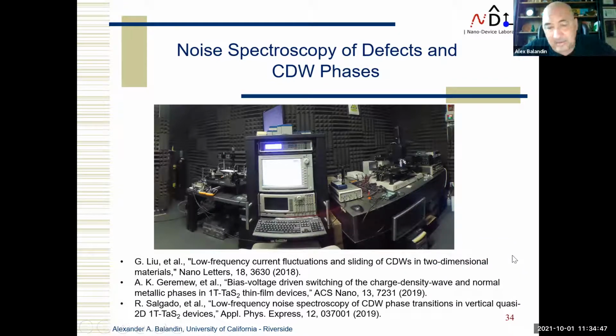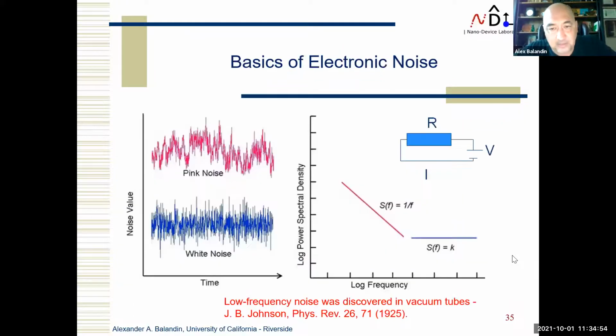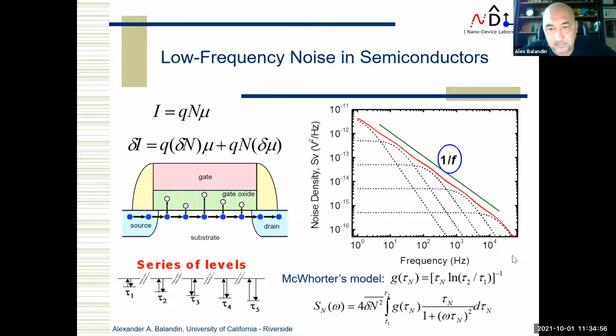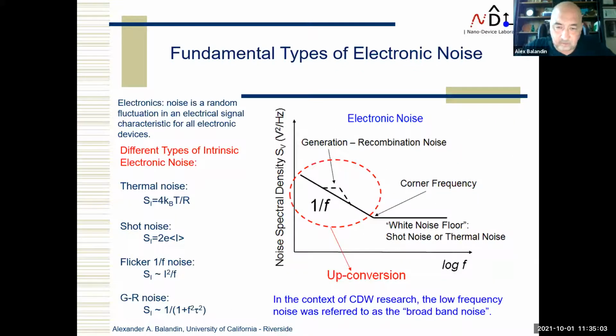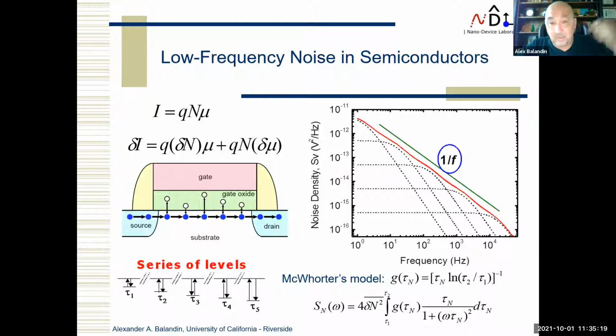And I already mentioned that we use noise spectroscopy to say something about phase transitions. I would like to skip this part because my time is limited. But essentially, we measure the noise response in this low frequency domain, from 1 Hertz to 100 kilohertz. And this is very informative. It's sensitive to defects, which act as trapping centers. And it's also sensitive to phase transitions. When something happens with the lattice, the noise peaks, so we use this property.